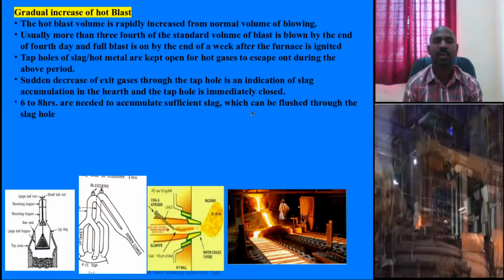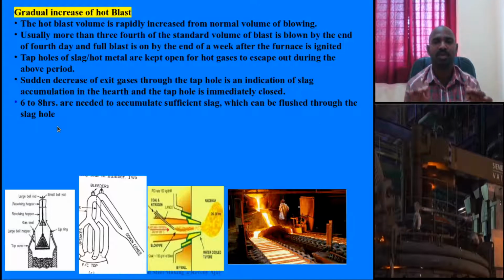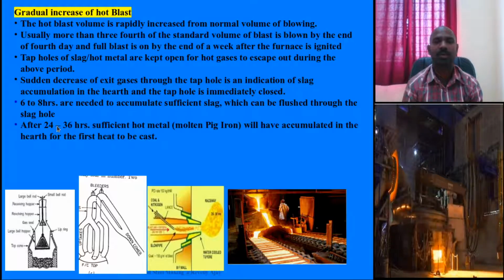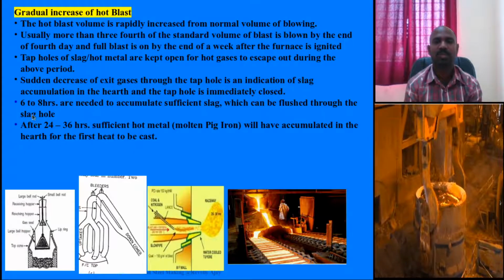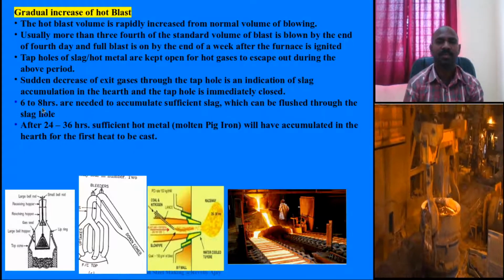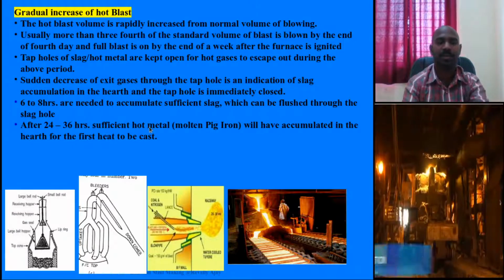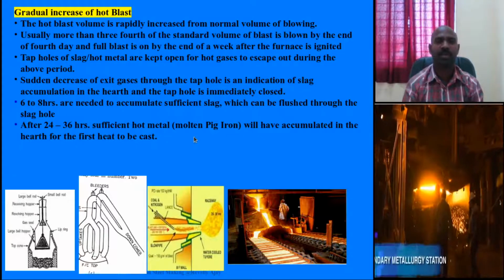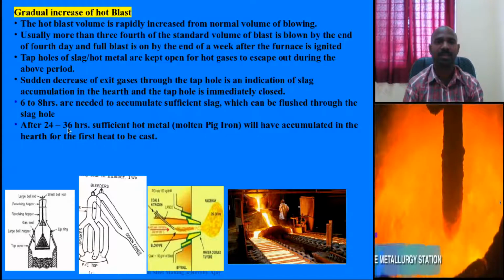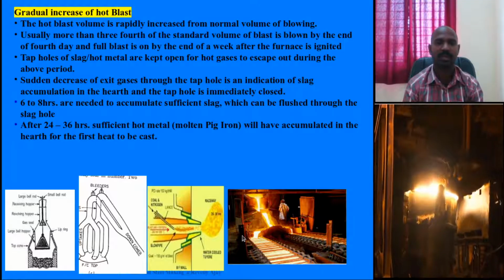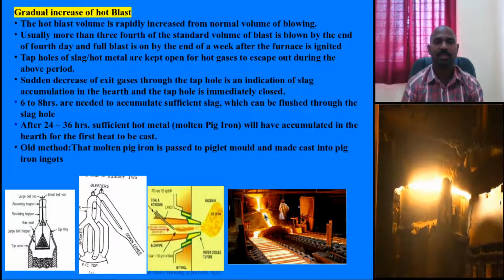Then you will open the slag tap hole, keeping the iron tap hole closed, and remove the slag. It will take a few hours. After that, you will wait for 24 to 36 hours to accumulate the hot metal. Then you will open the hot metal tap hole. After waiting that time, you take it out to the ladle.